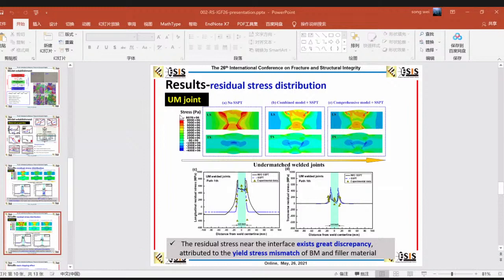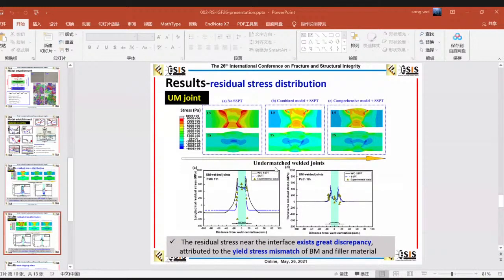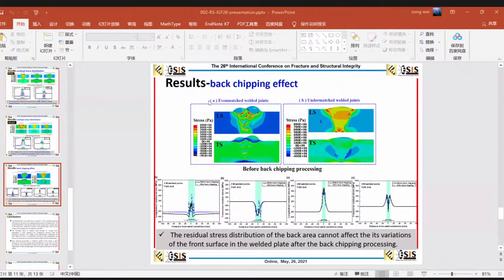So this is the undermatched welded joint. Because there's no SSPT effect in the undermatched weldment, the residual stress near the interface exhibits a great discrepancy, attributed to the yield stress mismatch of the base metal and the undermatched material. Also, we consider the back chipping effect. So I think the residual stress distribution of the back area cannot affect the variations of the front surface in the welded plate after the back chipping processing.